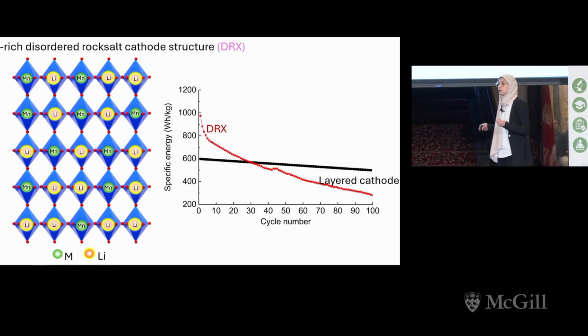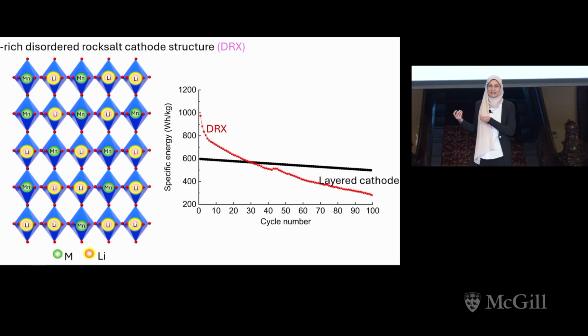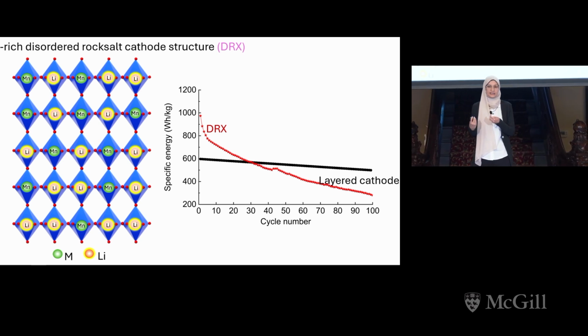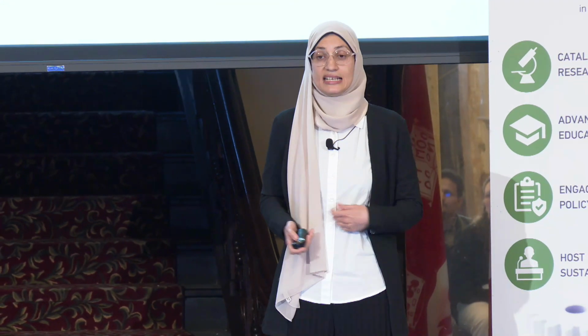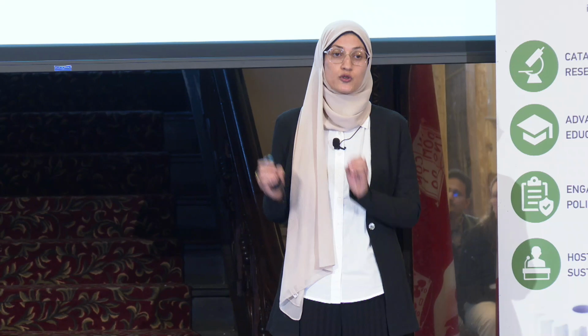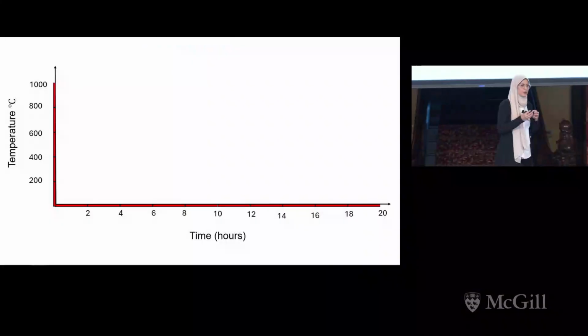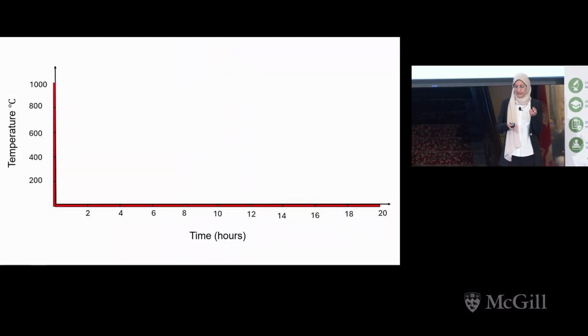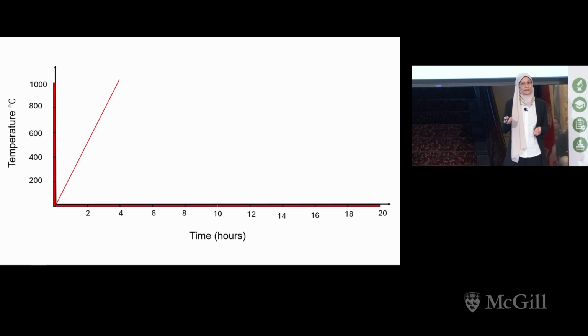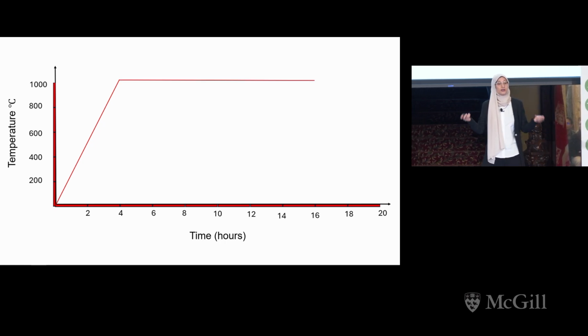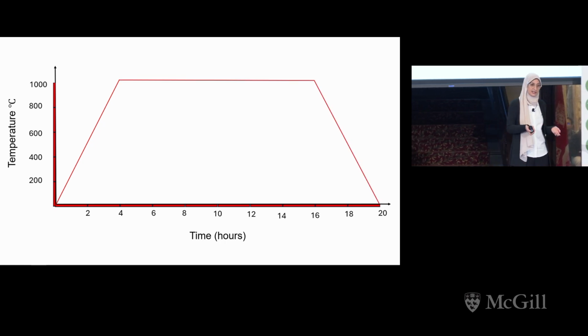First, I tried to understand why the energy density of this material declined quickly. I looked into the literature and found that the main issue is the synthesis method people use to make it. When people try to make DRX, usually they mix solid precursor, and because the reaction is solid-solid, it needs high temperature like 1000 C and long time like 12 hours in order to be synthesized.